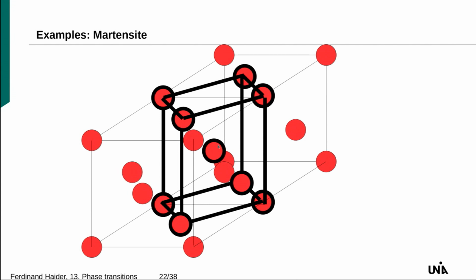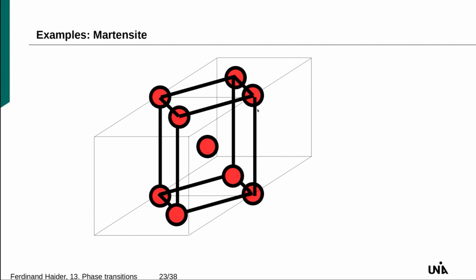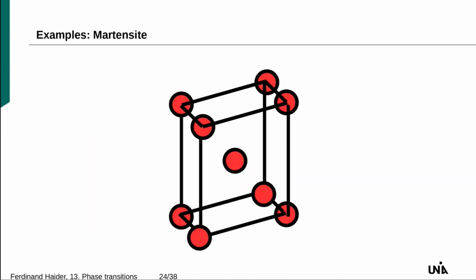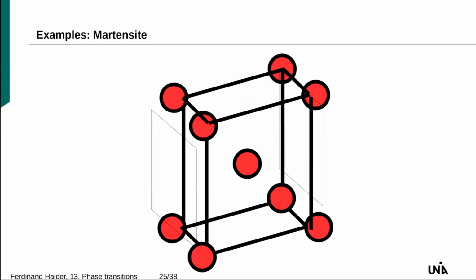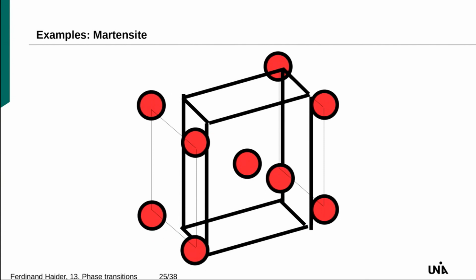And now if you want to transform from this FCC or body-centered tetragonal phase into a body-centered cubic phase, you just have to slightly displace the atoms. And this is what is known from these displacive transformations. You slightly shift the atoms, and you do it the same in all the unit cells. So they do it all in parallel.